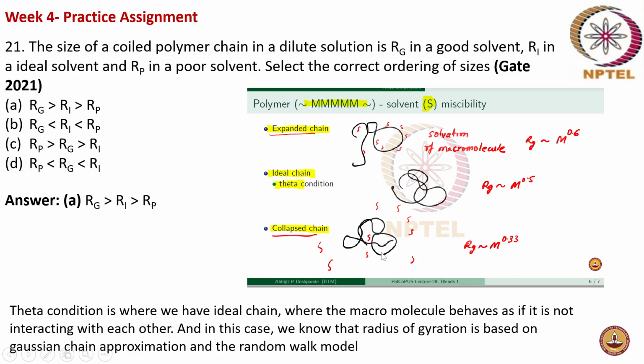And finally, in a poor solvent, there will be more polymer-polymer interaction, right? And it will tend to have more of a coiled state, ending up having a very low radius of gyration, which is related to the molecular weight as M power 0.33. Okay, so that means in a very good solvent, the radius of gyration will be maximum, highest, followed by ideal solvent, because the molecule behaves as if there is no interaction with each other, and then followed by poor solvent, where it will be in a completely coiled state. Okay, ma'am. Yeah, got it.